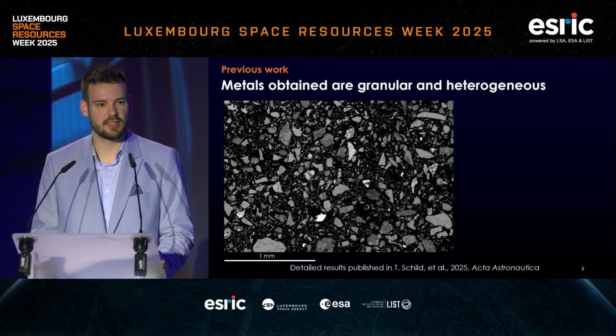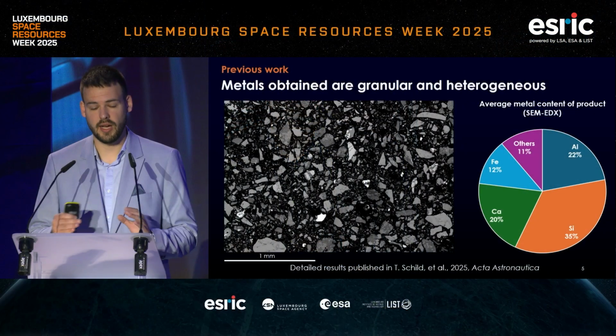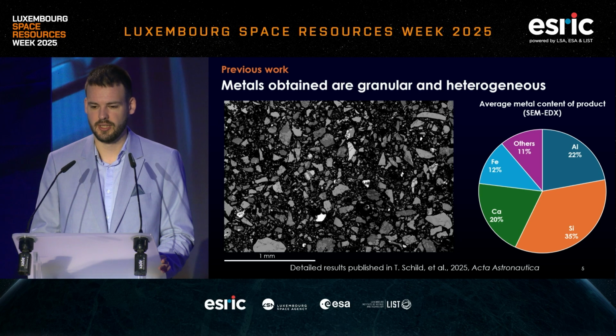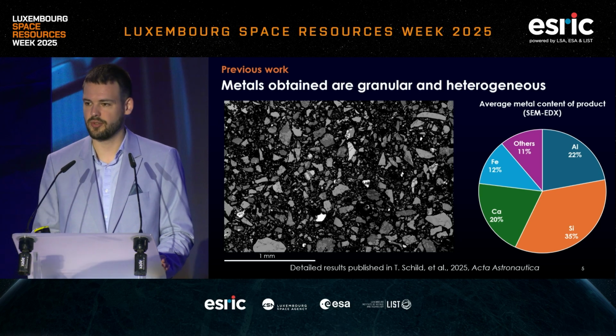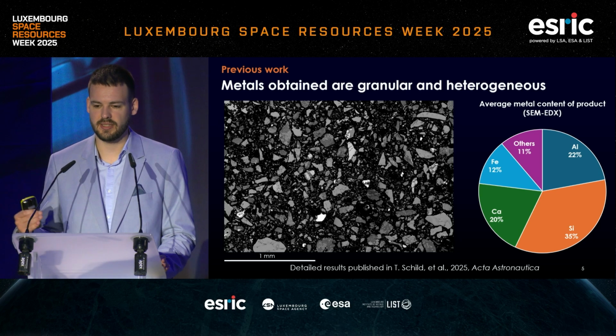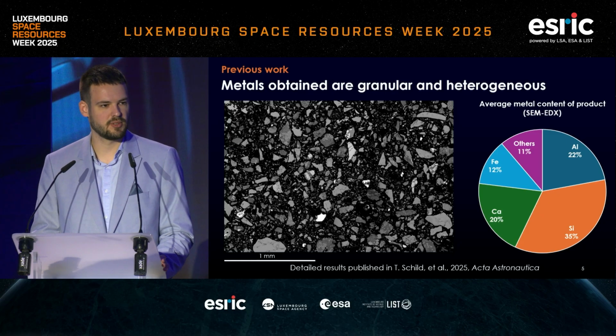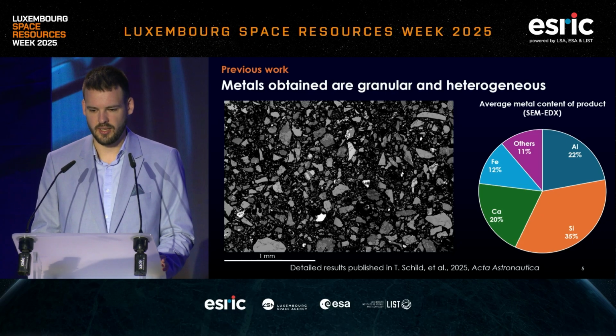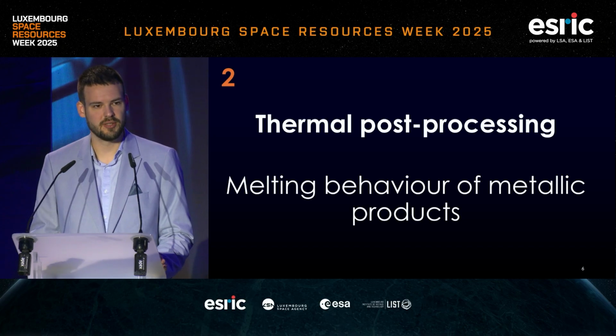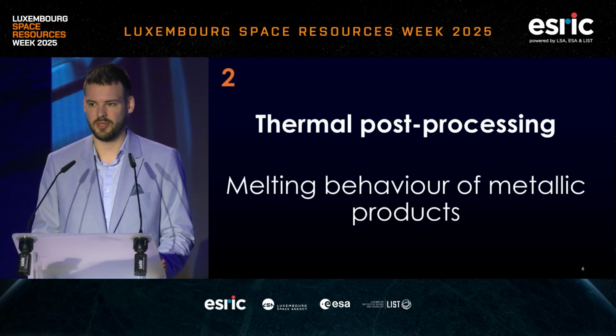We have a publication that came out earlier this year. I obviously invite you to have a look at it, and afterwards I'm happy to discuss some parts of that. The only thing I'm going to tell is the average bulk composition we observed in this material is, as you expect, most of the metals you put in come out. So you get mostly aluminum, silicon, calcium, and iron, as well as some contaminants from the process. So now I'm going to talk about what we've been doing during this current year. So we have been looking at the thermal post-processing of this material and how we can turn it into an ingot or a billet that can be used for manufacturing.